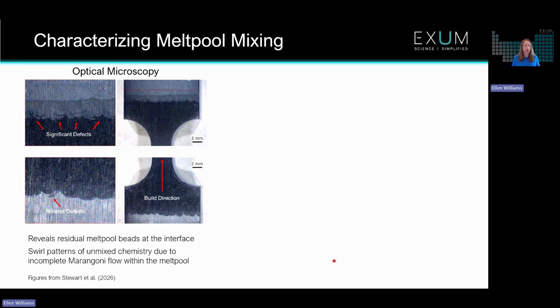But first, we're going to look at some optical microscopy images. So first, these tensile bars were ground, polished, and then etched so that the different materials were obvious in this optical microscopy view that you're looking at here. I'll point out that this was before any sort of mechanical testing was done. So this is just the tensile bar before it was broken. And what you can immediately see are these curved patterns here that represent the melt pool beads. So as the DED printing process is moving from one layer of stainless steel to one layer of nickel alloy, the laser melts a specific area and creates this melt pool.